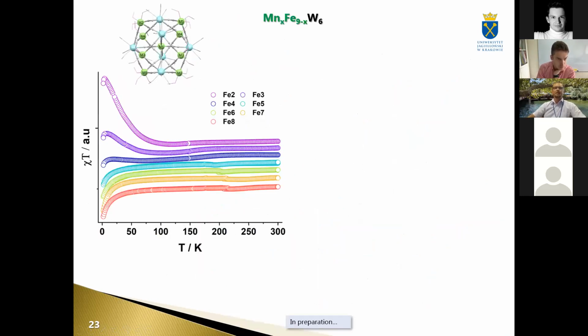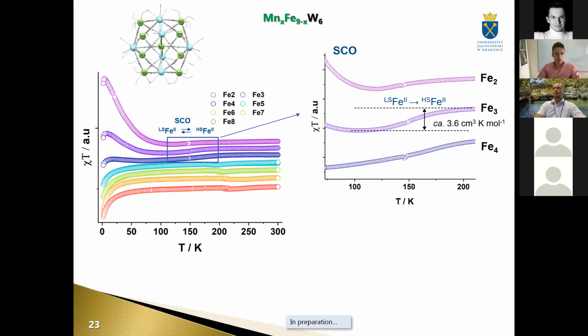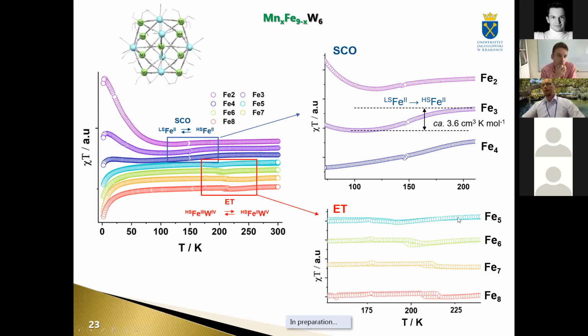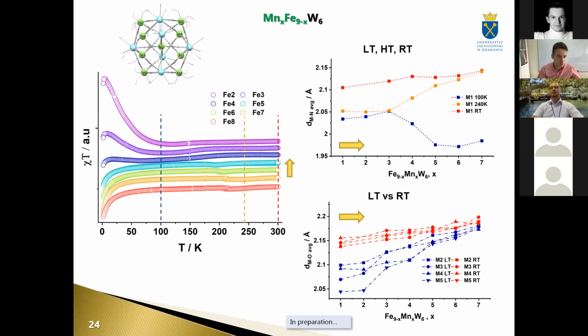Another series is the series where we mix iron-2 and manganese-2 in these green sites. And again, we have two regions. In manganese-rich phases, we have something which looks like spin crossover, and in iron-rich phases, we have definitely something which looks like electron transfer. And moreover, the position of the transition is shifted towards lower temperature with the decreased amount of iron. So this is somehow consistent with the data which I showed you before. So this material is now under preparation.